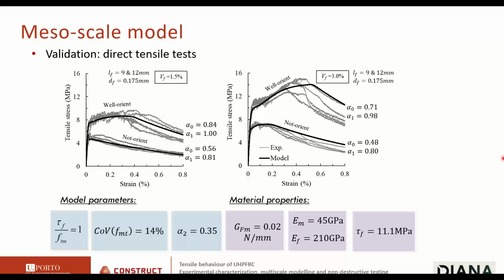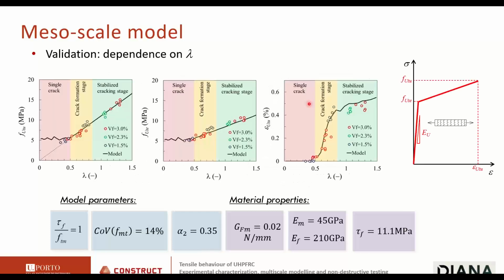So how does this compare with experiments? Well, it compares reasonably well. So you see here tests on UHPFRCs with different fiber contents, different fiber orientations, and with the same set of material properties, same set of model parameters, we could get a reasonable fit to what we observed.